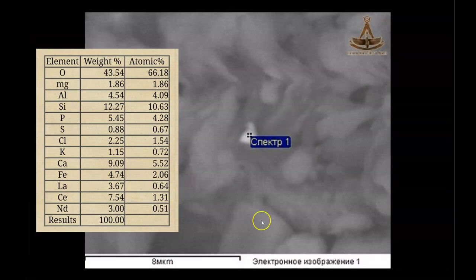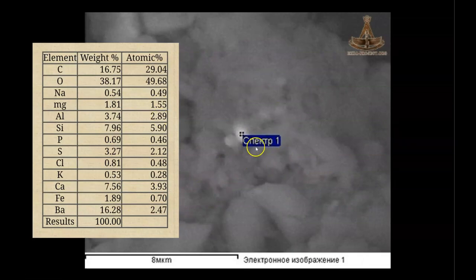Next up, the scanning analytic electron microscopy. And remember that this is an instrument used to examine tiny microscopic particles and determine their composition. So this first one is described as a small grain of phosphorite enriched with rare elements, typical of precipitation. The analysis is dirty and captures the matrix, meaning this microscopic grain is embedded within the surrounding material and is naturally occurring. But it does have the phosphorus here and those rare earth metals, lanthanum 3.67%, cerium 7.54%, and neodymium 3%.